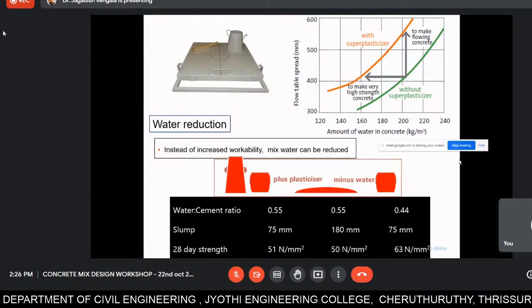So you can see, based on the flow table spread, the amount of water in concrete, to make very high strength concrete, the amount of water we go for is like 160 to 140 and so on. This is up to 160 without superplasticizer. With superplasticizer, you can come down to 140, 135. If you want to make flowing concrete, without superplasticizer, you can go up to 240. And with superplasticizer, you can reduce it to 200, 220.